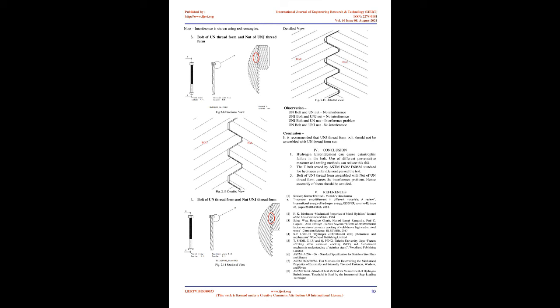The wedge was of hardness 45 HRC, thickness equal to one half the nominal fastener diameter (i.e. 0.125 inch), and angle should be 6°. The T-bolt was tensioned to 75% of their specified minimum ultimate tensile strength. The assembly was kept in this tightened state for not less than 48 hours, after which the test fastener was visually examined for embrittlement-induced failure such as missing head. The joint was then disassembled and the test fastener visually examined using 2–4x power magnification for evidence of embrittlement failure such as transverse cracks in the shank, threads, or at the junction of head to shank.